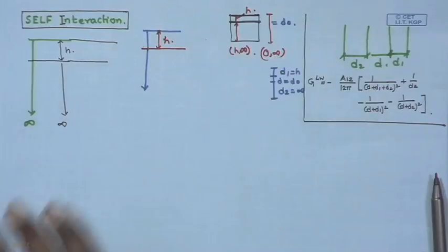Now, you are neither creating any matter nor destroying any matter, mass remains conserved. So, why do you need to supply this extra energy? Well, you essentially need to supply this extra energy to create these additional interfaces which get generated by cutting. Now, suppose we do the same thing, we cut this block of material over here at a distance h, let us say from the top, and we keep it placed over there.